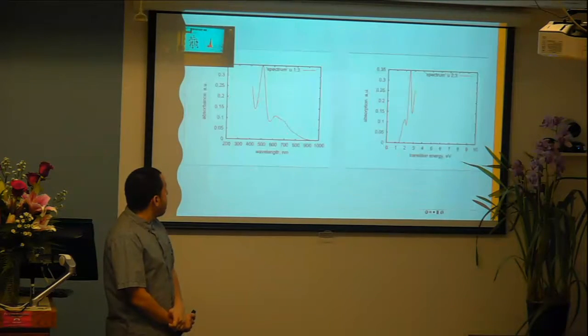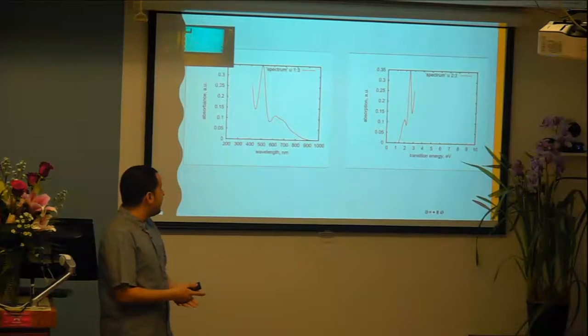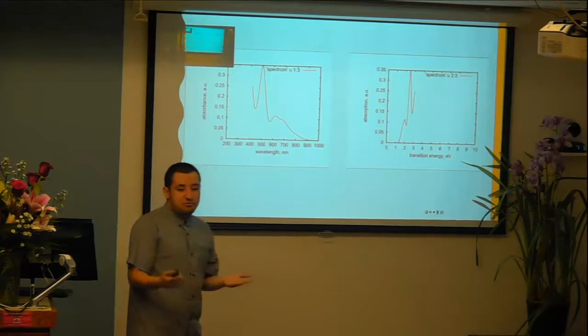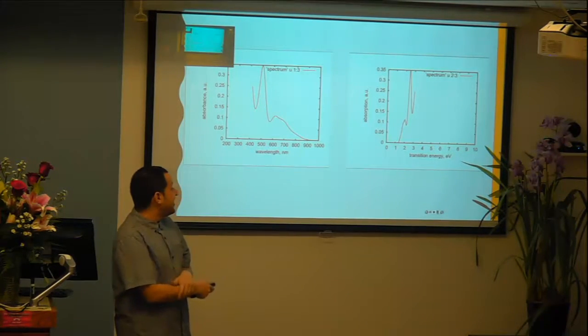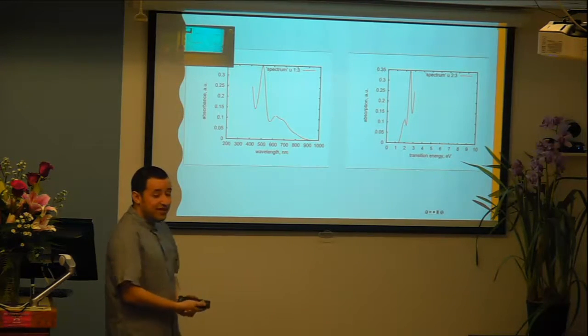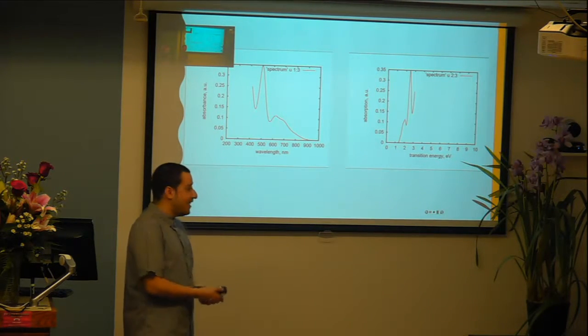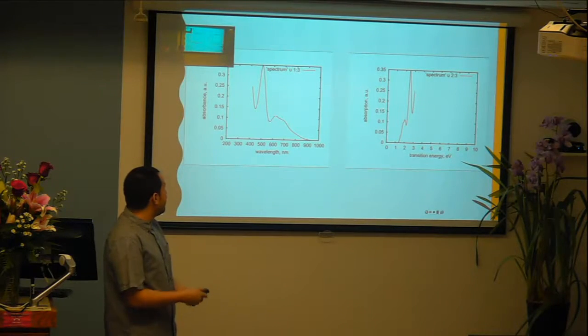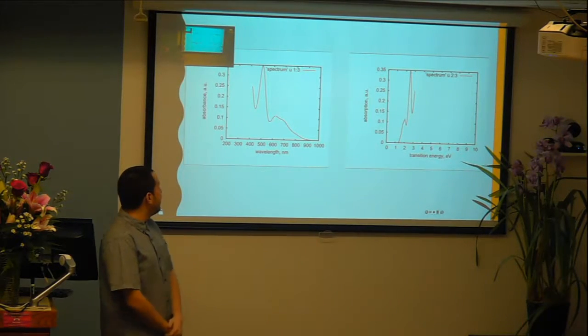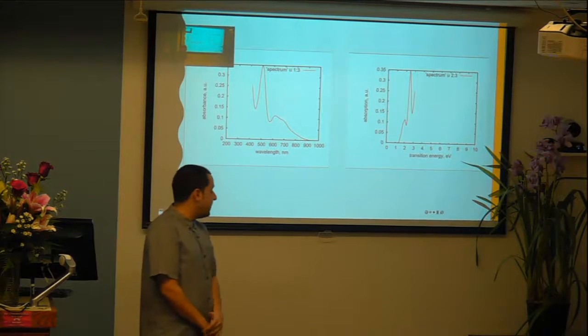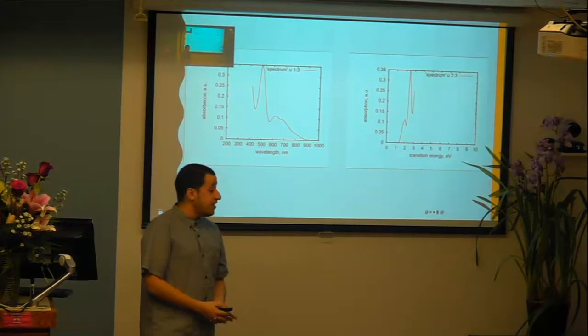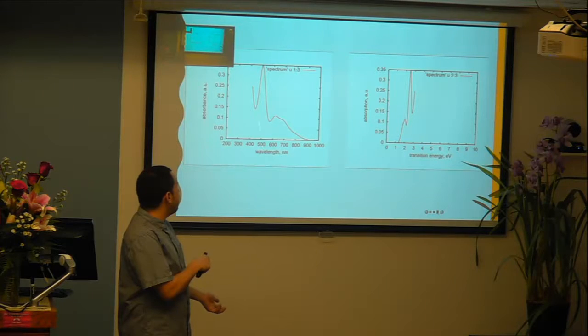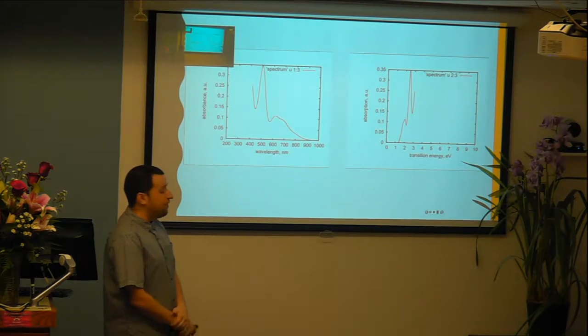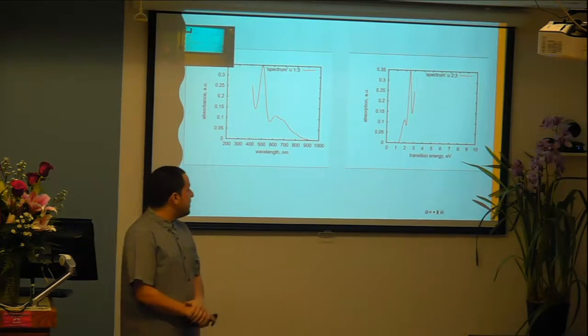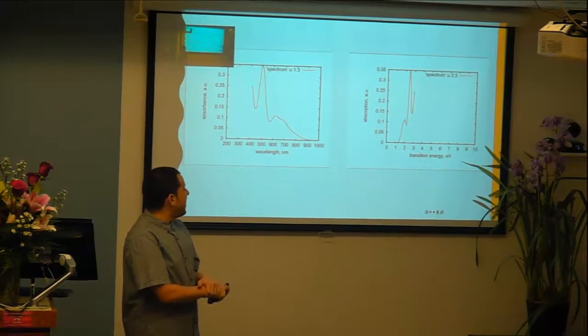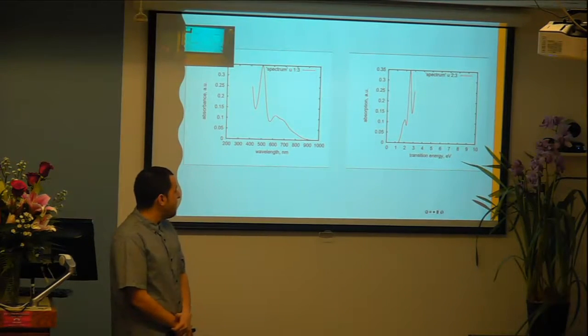And well, after that, we were able to find absorption. I'm not sure whether people in the crowd like electron volts or wavelength. I'm more of a wavelength person, but I don't discriminate against electron volts. So basically, we have a high peak around the visible range, usually in about the green range at 500 nanometers. And if you do like electron volts, we have a high transition at about 2.5.